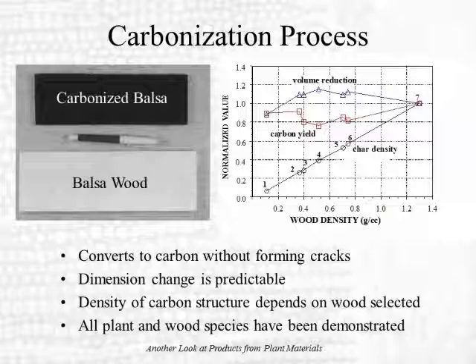When you look at the char density, the char density follows nicely along with the wood density. On the y-axis is a normalized scale for whether you're looking at char density, carbon yield, or volume reduction, just so I could throw it onto one busy graph. Normalized to the heaviest wood sample.